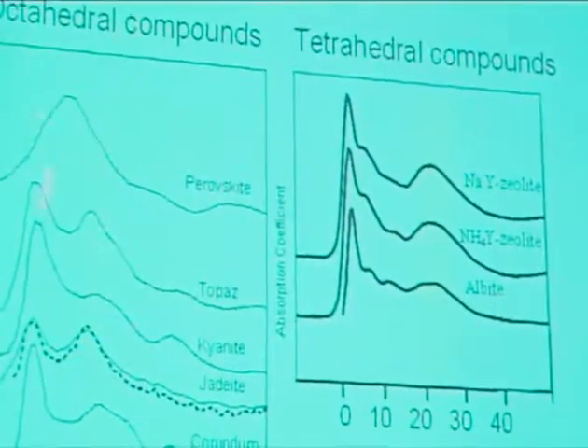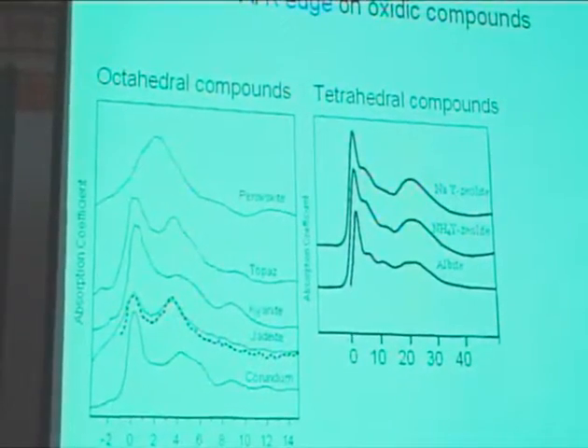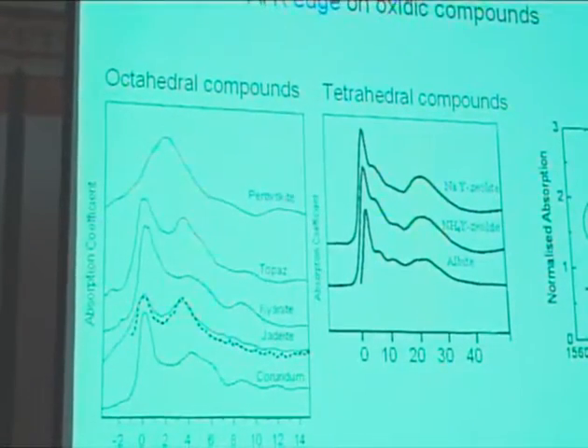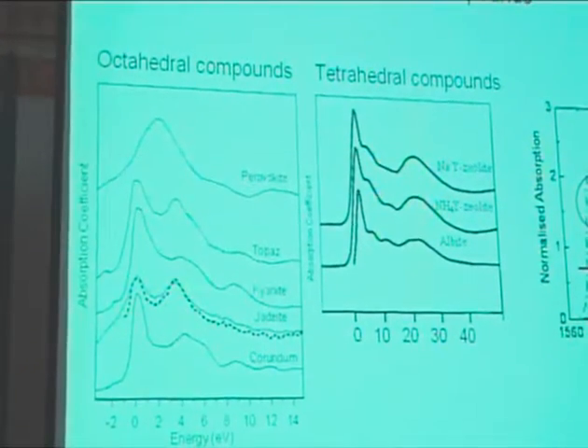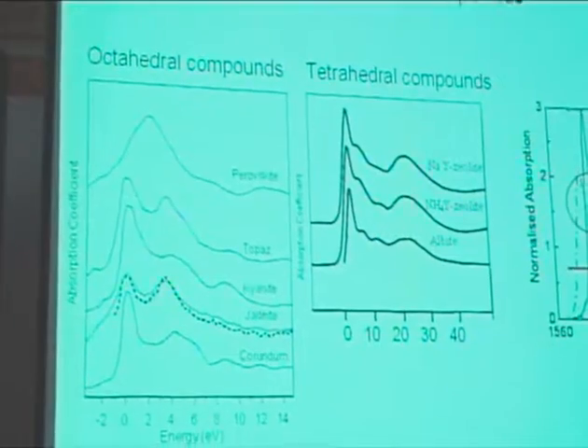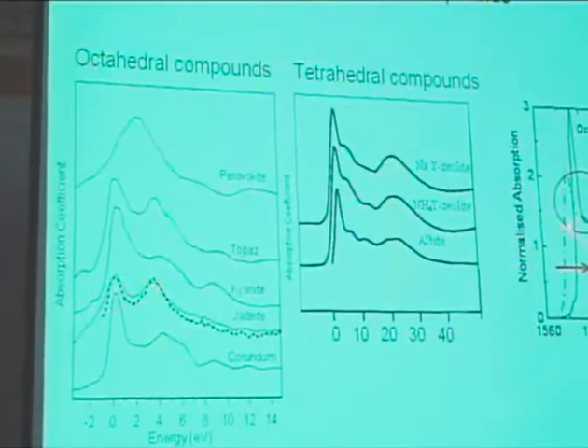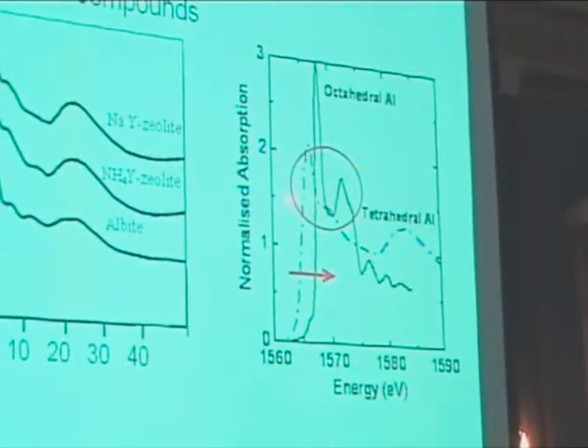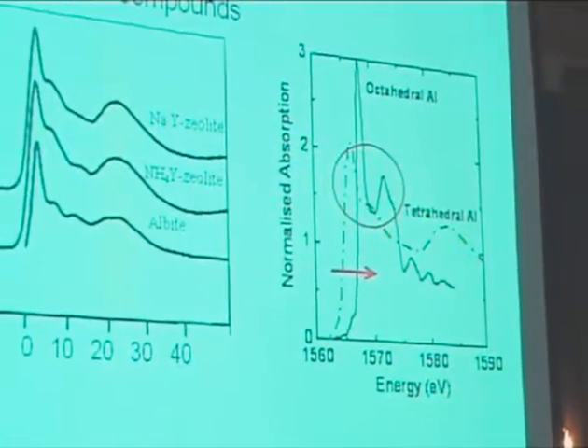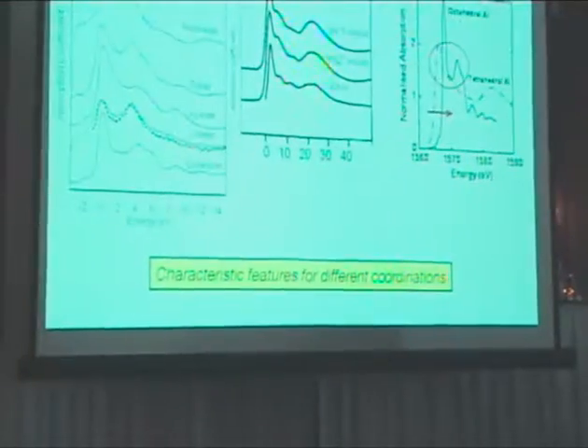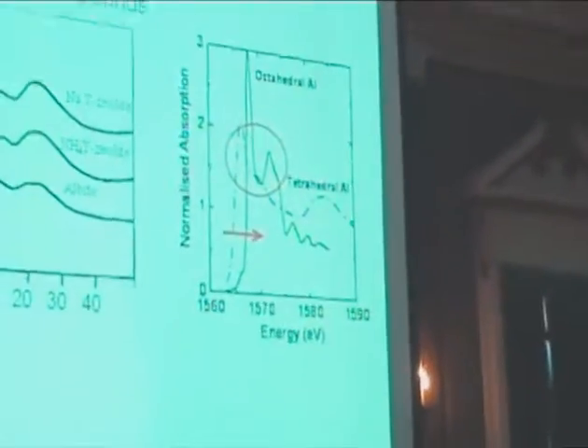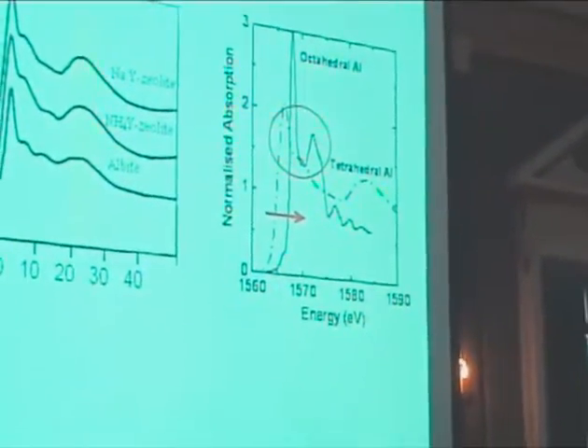For instance, here you see zeolites, you see a peak here and a peak there, and these are all octahedral compounds and these are tetrahedral compounds. And you see there are differences. When I plot them over each other, you see that the octahedral has two peaks close to each other, and the tetrahedral has this broad one here and a peak more to the left. So if a peak comes up here, we know it's octahedral, and when we start tetrahedral, and things like that. So we use this in the fingerprinting way to see if our dealumination of zeolites is successful. Did we remove it fully, or did we transform it into octahedral or whatever?